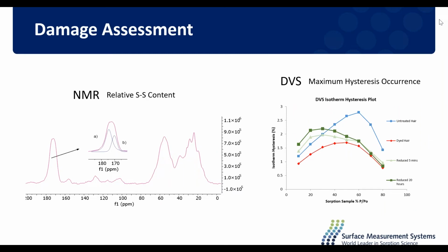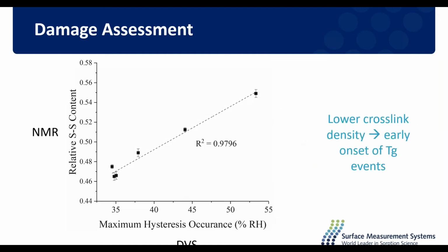But to sort of prove this and to see how our NMR data can help us here, we wanted to see if we could correlate the crosslink density of the samples to that occurrence of maximum hysteresis, or where the onset of glass transition events occurs. And that correlated really nicely. We see this strong correlation showing that for those hair samples with lower crosslink density, we are getting that maximum hysteresis occurrence at much lower relative humidities, indicating an earlier onset of glass transition events.